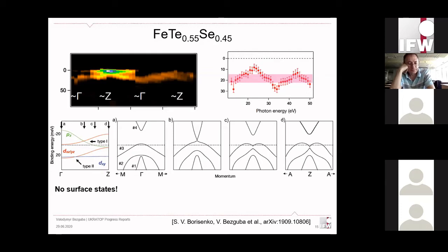And if we analyze this, we see that there is no inverted gap because pz doesn't cross dxz, dyz. It almost crosses, and even if there was an inverted gap, the size of it would be diminished due to renormalization. Renormalization is the difference between the calculated band structure and the real band structure you see in the experiment. From calculations, the gap might be expected if the scenario is slightly different. If it indeed crosses, it is expected to be several meV, which means that in reality, the real size of the gap would be like 1 meV or even smaller, which is not possible to see with ARPES.